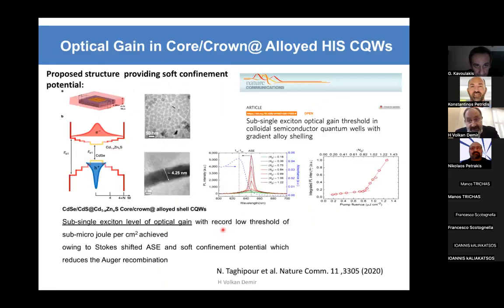We wanted to do better than that. And up to now, I talked about core crown shell structure, but what we can do is we can alloy this shell carefully. And in alloying, we can generate these soft transition barriers. We carefully quantum mechanically calculate these, design, and then implement such that we have the highest gain capability. And indeed, in the ensemble, with this type of core crown alloyed shell colloidal quantum wells, we were able to